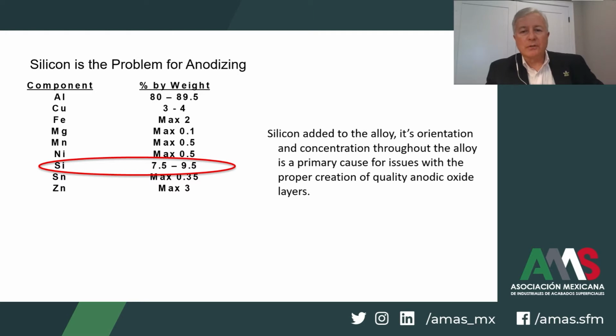During surface finishing operations, not only the concentration of the silicon that's added into the alloy is important, but the actual orientation of the silicon or if there's any concentration gradients because of a tempering process during the part manufacture becomes really a concern for the applicators. And it's difficult to overcome to make quality oxide layers. Remember that when we're anodizing or creating an oxide layer, we're dissolving the aluminum, and the metals in the alloy cause problems too. So we have to overcome these. For example, copper is a concern in these alloys because you get copper smuts. And the silicon smuts that form can be difficult to remove before the anodizing process. And that's the difficulty in taking care to manage the silicon so that we can successfully anodize these alloys.